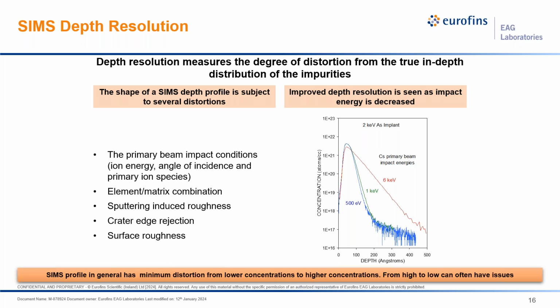At 6 kilovolts, you can see that we can measure the ion uprise. Basically, the front portion seems not to be as distorted, but there's what's called the knock-in effect, where atoms are further pushed into the sample. So this tail that we have here, this tail is distortion, it is all artifact. As we lower the primary ion energy, we can retain more of the original information, until finally at the lower primary ion energy of 500 eV, we have much more of the original implant shape of the profile.